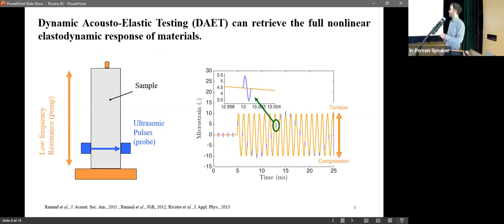We have a low frequency, large amplitude vibration, and for that particular example, we resonate the sample on the first compressional mode. And we oscillate at a large enough amplitude that we are going to disturb the elastic state of the sample. And then at the same time, we use a pair of ultrasonic transducers at high frequency. We send tiny pulses to monitor the elastic state of the sample. We start by probing and the pump is not activated. Then we activate the pump. And then you see that some of the pulses are going to be sent during the tension phase. Some pulses are going to be sent during the compression phase. So we are able to track the changes in wave speed as a function of strain.